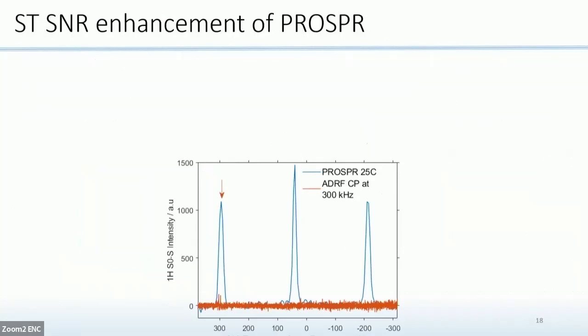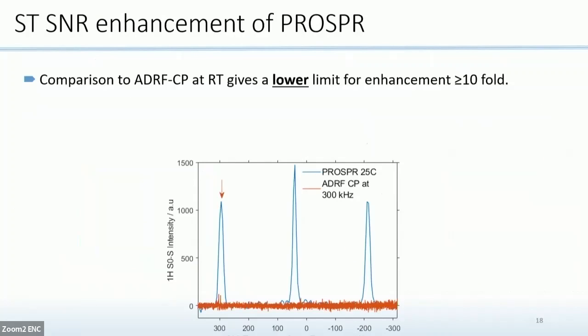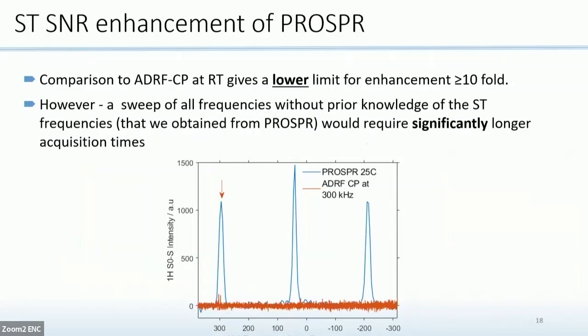So if we go back to trying to estimate the SNR enhancement, in comparison to the PROSPR, I measured an ADRF-CP spectrum at an offset of 300 kilohertz in orange here. According to this, this gives us a lower estimate for the SNR enhancement of a factor of 10. But this is actually an unfair comparison for us, because the only reason I knew that the satellite transition was here was because I previously measured it by PROSPR. So if I would actually have to sweep all the frequencies and then get sufficient SNR, I think a fair estimate of SNR per unit time would be at least 100.